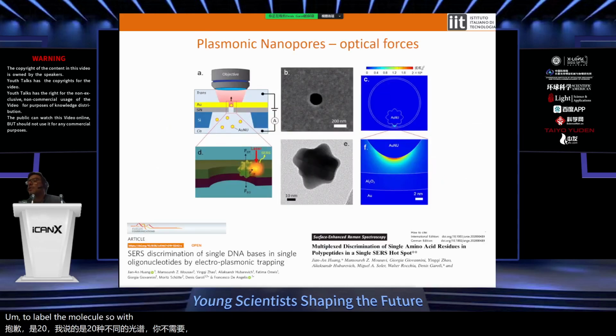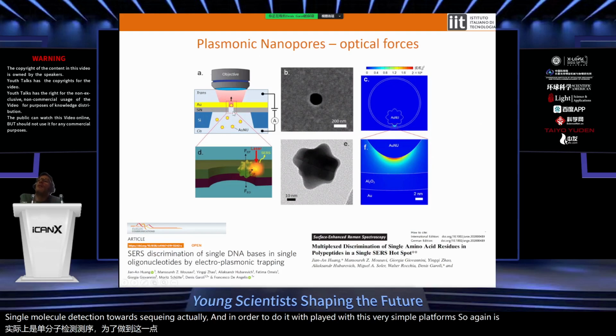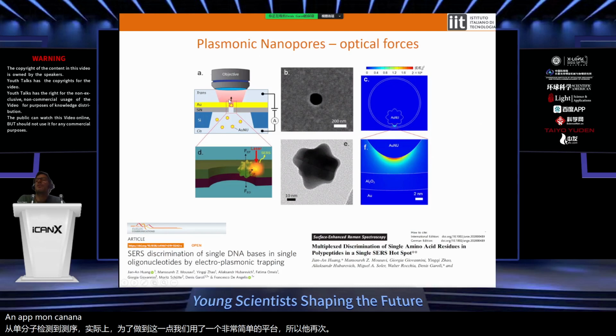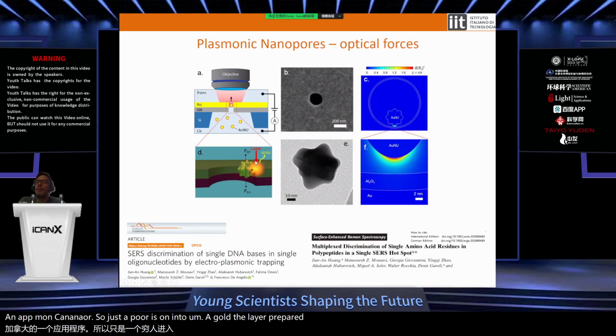So we demonstrated that Raman is a very powerful technique to perform single molecule detection towards sequencing, actually. And in order to do it, we played with this very simple platform. So again, it is a plasmonic nanopore, so just a pore in a gold layer prepared on a silicon nitride